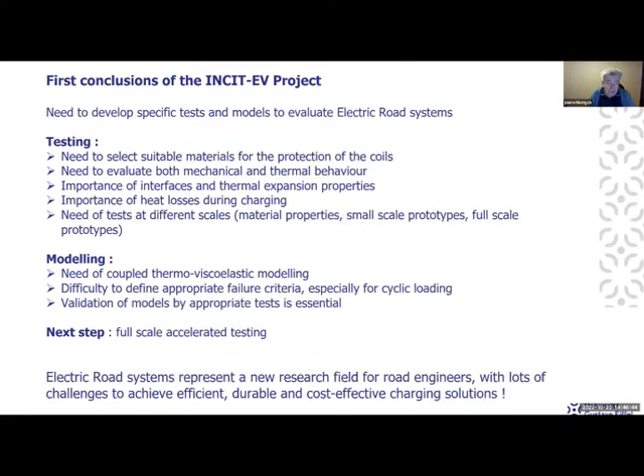So just in conclusion, our first conclusion is that to study this electric road systems, it is necessary to develop specific tests and models, which are not the standard models used for pavements. And for testing, there is a need to select specific tests to evaluate these solutions. And there is a need to select suitable materials, to evaluate both the mechanical and thermal behavior, to evaluate the behavior of the interfaces, and also to look at the thermal expansion properties of the materials. And then you need to evaluate the heat losses during charging and take into account the heat losses during charging.